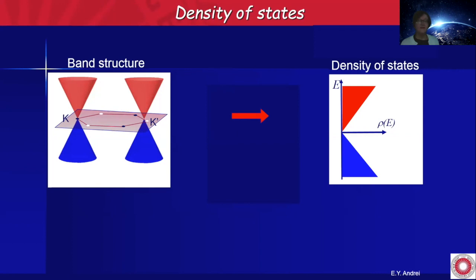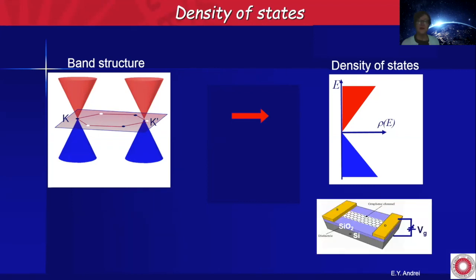Now, this conical band structure gives rise to a linear density of states, where the number of states that are available per unit energy vanishes here at the Dirac point. And that is crucial for the properties of graphene, because it's very easy to move the Fermi energy within this band structure. It takes very few electrons to move the Fermi energy, and here I'm going to give you an example. Let's take a standard device where you slap a piece of graphene on a silicon wafer. You have 300 nanometers of silicon dioxide here. You have source and drain electrodes, and then you apply a gate voltage. So just due to capacitance, you are changing the number of electrons in the system, just capacitively.